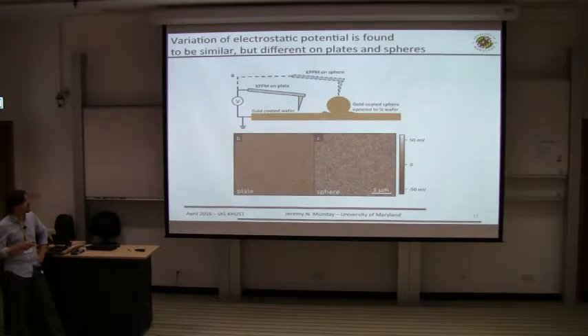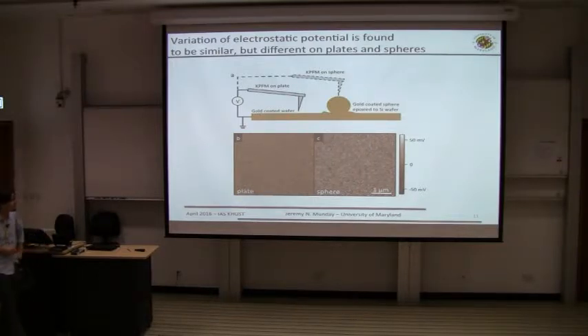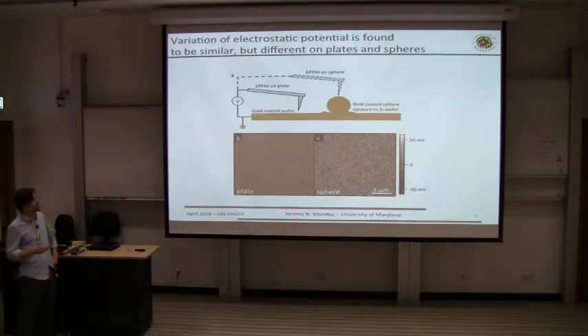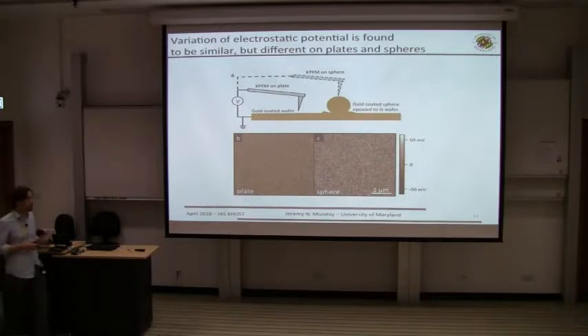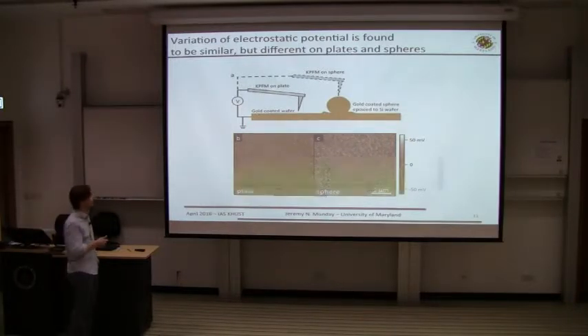And so this is not a sphere that would be used in an experiment, this is just for a proof of concept. But we deposited gold in the same manner on both of these objects. We had a sphere that was attached to a plate, just so we could look at what the patch potential variation is from one surface to the other. And so those are plotted here. And so you can probably see, even just visually, the color looks slightly different between these two. So you see, even depositing them in the same manner, that we are getting some differences in the way that the patches are distributed here. So it's important for us to understand that when we make our measurements.